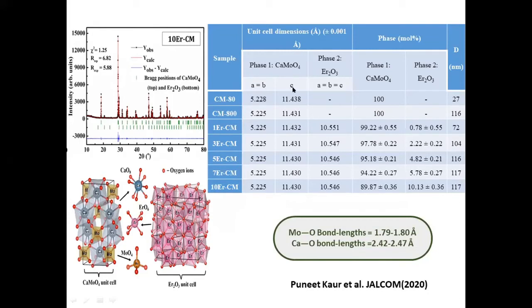A is equal to B, and that is not equal to C. And all the angles are 90 degrees. And from the synchrotron X-ray diffraction studies, we found that the two phases exist separately. The erbium oxide and the calcium molybdate peaks, you can separately identify from the X-ray diffraction patterns, and you can find the lattice parameters. You can find the position of the calcium ions, molybdenum ions, and oxide ions, and also